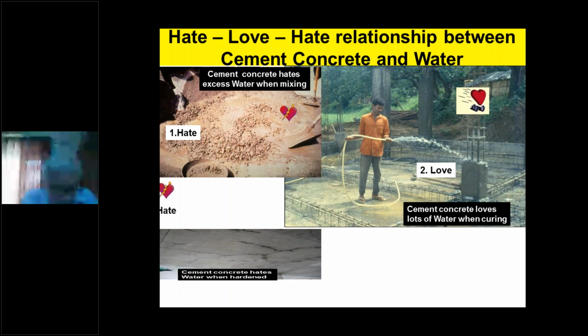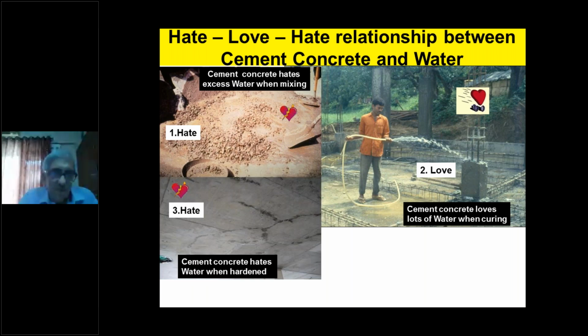Cement concrete hates water after it has hardened, because water enters the concrete from outside. Water carries harmful chemicals like chlorides and sulfates with it. The chlorides accelerate the corrosion process in concrete. Concrete has reinforcement in it, and this creates rust and debonding of reinforcement in concrete. Debonding means loss of strength. Debonding means the rust, which is now coating the reinforcement, starts expanding. The expansion causes cracks, more cracks in concrete, more ingress of water in concrete.